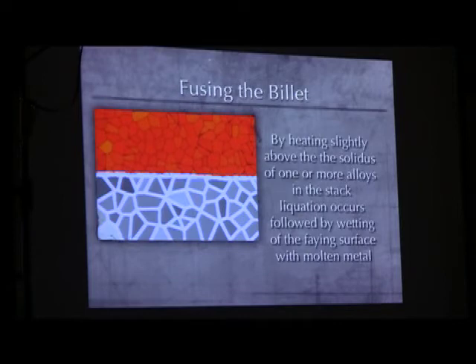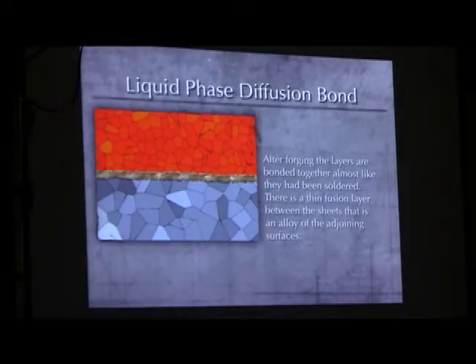One of the drawbacks to this is that the liquid that flows out of the matrix to go along that capillary attraction between the sheets leaves voids in the matrix, so you have a very weak metal matrix left behind, and that's why you have to forge it to close up that matrix and to heal those openings up. And once it's cool, if you would look at it with a microscope and careful examination, you would actually see the two parent layers on either side, and you would see a third material, just like a solder bond, but very thin between the sheets.